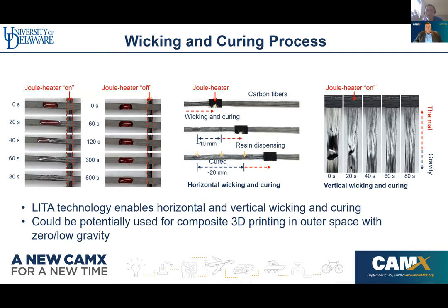Once we move the Joule heater, touching the carbon fiber along the surface of the carbon fibers, and then we deposit the liquid resin, you can see the whole filament surface can be cured. And on the- Dr. Fu, we're running out of time here. Okay, I will be quick.